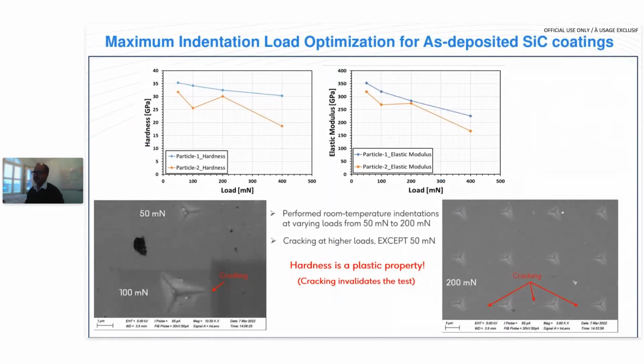But for silicon carbide, which is ceramic, when I mentioned that we used 50 millinewtons as a maximum load, the idea was that since we're going to perform these indentations on a ceramic coating, which was brittle, we need to know what the maximum load is that we can use without cracking to perform our indentation testing. So we optimized the maximum load for as-deposited silicon carbide coatings and surrogate TRISO particles.